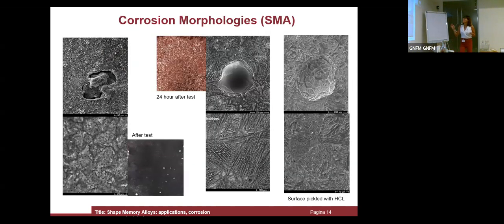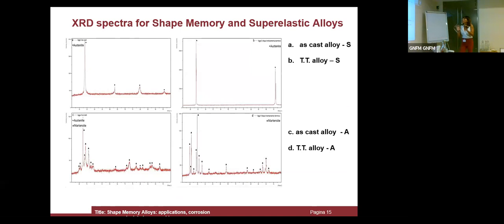Here I would like to show you some corrosion morphologies before and after the test with different etching of the surface. In fact, the surface can be pickled with a different kind of acid in order to show the structure better, to have, from a metallurgical point of view, a better understanding. Finally, we try to compare shape memory alloys with the superelastic alloy.